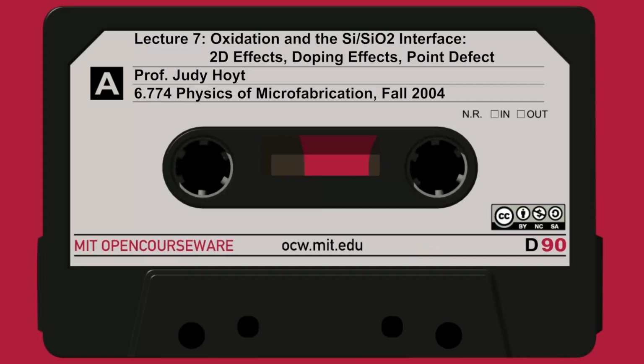So then the K sub s in the curved or stress case is just the ordinary K sub s times these two exponentials. Again, this is an activation energy, either the sigma n VR over kT and a sigma t term. So basically, the surface reaction rate is going to go down, and the amount it goes down will depend exponentially on these two stress terms. And these are fitting parameters that you can put in the model. And so you can see how you can introduce a temperature dependence to this effect; how strongly temperature dependent it is will depend on the numbers you put in for VR and VT.